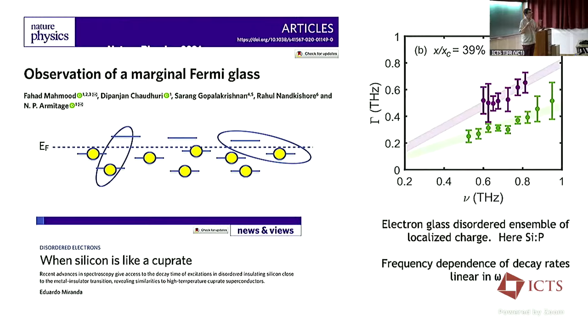There's a way of understanding this in terms of emergent dipole degrees of freedom, and this was one of the reasons that we were interested in looking at that. We know what to do with a two-level system like that in terms of modeling its nonlinear response. One of the things that we found was that we could measure the lifetime of these excitations versus frequency, and found that their lifetimes were linear in frequency with a coefficient very close to 1.